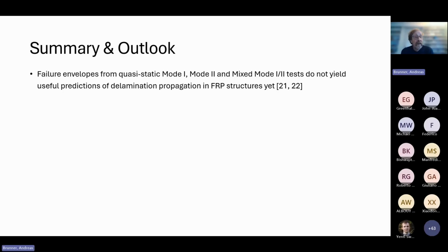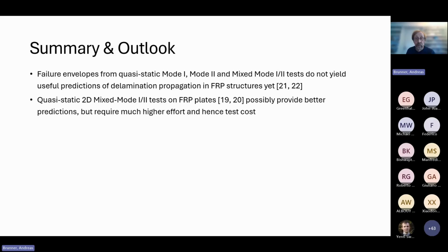Now, as a summary and outlook, if you take these failure envelopes from quasi-static mode 1 or mode 2 or mixed mode tests, we do not get, what I would call, useful prediction of the delamination propagation behavior in real FRP structures. This is discussed in two references, for example. If you run the tests on something like square plates, as shown in the previous slides, then we possibly could get better predictions, but of course it's much higher test effort and also higher test costs. And the question is, is it worthwhile?